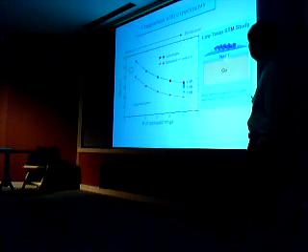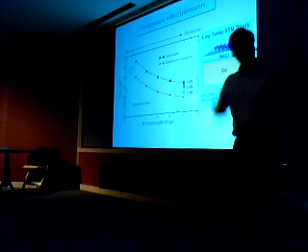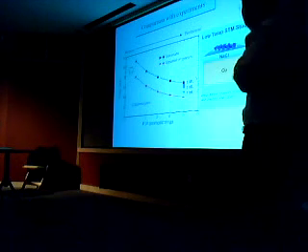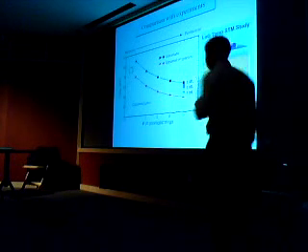polarization or correlation effects. Recently, there have been some STS experiments looking at the HOMO-LUMO gap of pentacene with layers of sodium chloride, an insulating material, in between copper and the molecule. So you see that as a function of the number of layers, it converges to the isolated molecule case. So you see that indeed the interfacial interaction, this kind of screening effect, is very important.